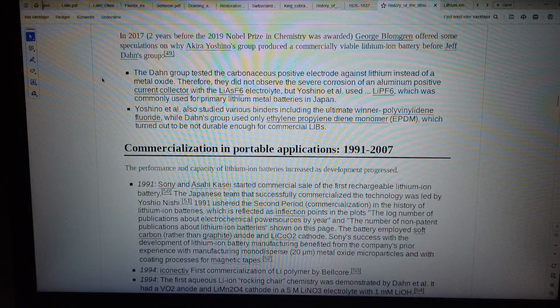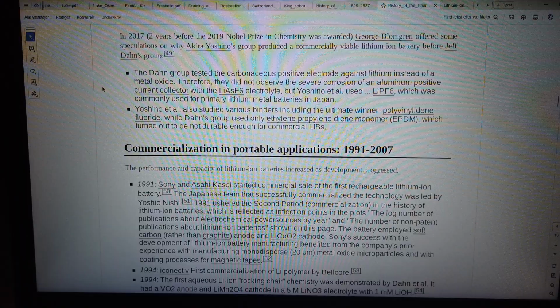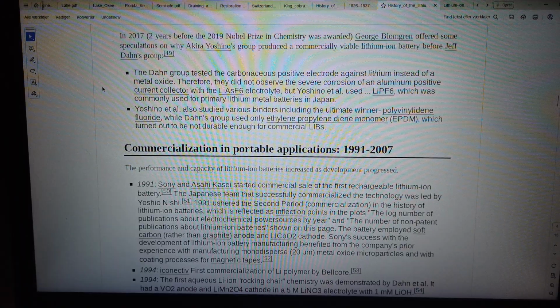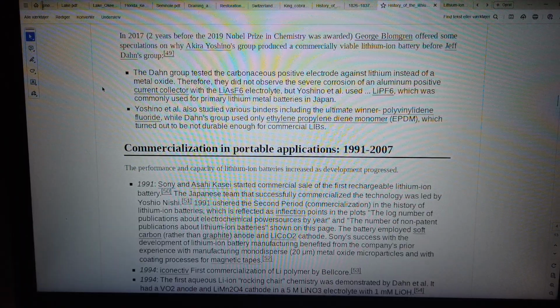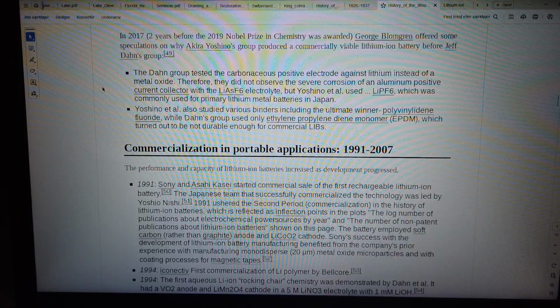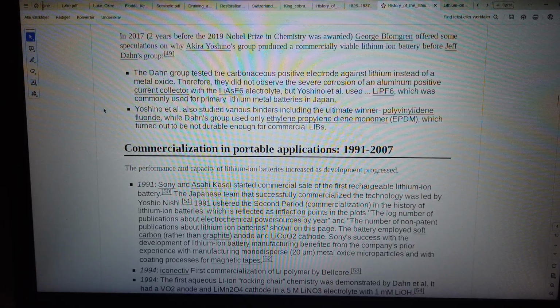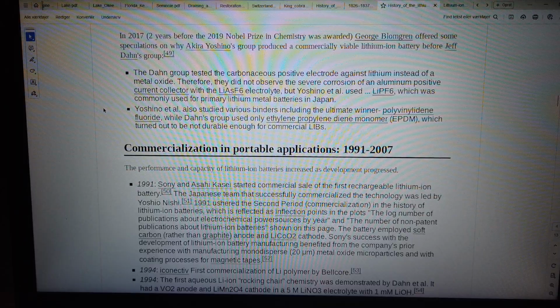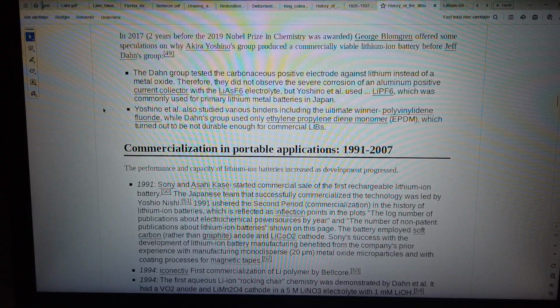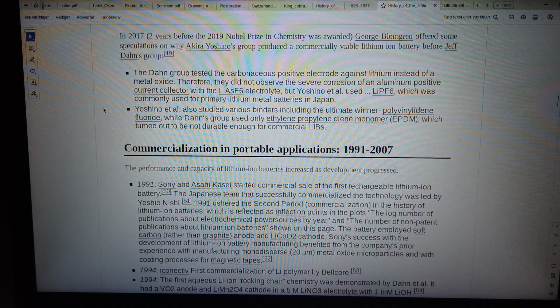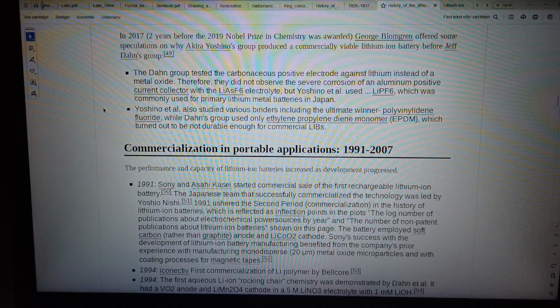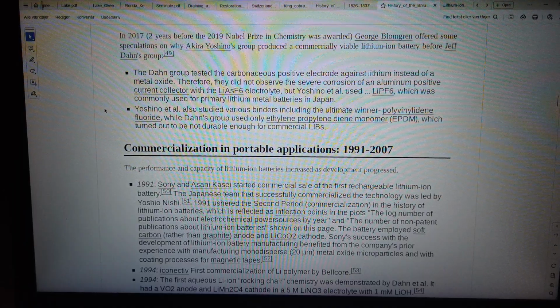Therefore, they did not observe the severe corrosion of an aluminum positive current collector with the LiAsF6 electrolyte, but Yoshino et al. used LiPF6, which was commonly used for primary lithium metal batteries in Japan. Yoshino et al. also studied various binders including the ultimate winner polyvinylidene fluoride, while Dahn's group used only ethylene propylene diene monomer, EPDM, which turned out to be not durable enough for commercial use.